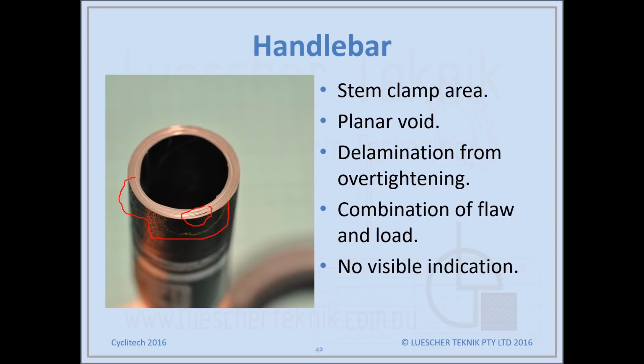So there's no visible indication on the surface, and in this case obviously the handlebar was scrapped because we cut it in half. And so it's important to not only tighten your stem clamp correctly and evenly to the correct torque, etc., but also to make sure that it doesn't have any stress concentration points on it. So that the stem has nice round corners, etc., like no sharp edges that really can lead to sort of pinch failures and other problems on the handlebar.